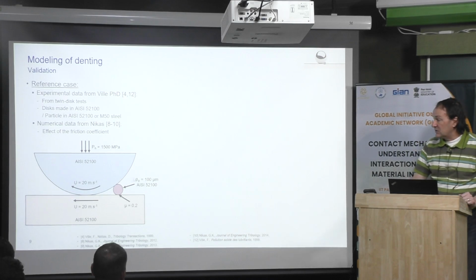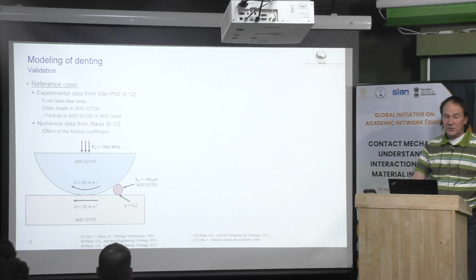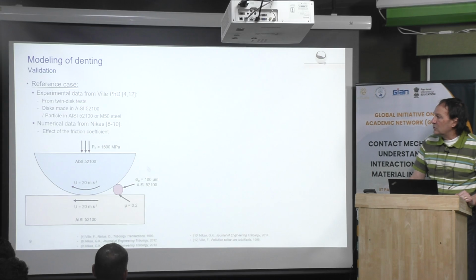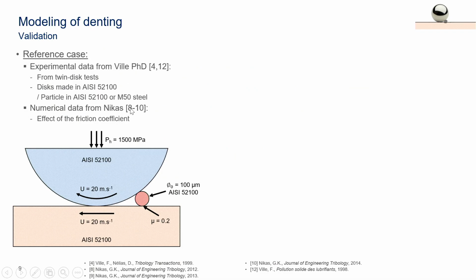Okay. The size is quite large, but this is a reference case, and we were able to do simulation with smaller or bigger particles. And also we compared to some data from experiment and from the literature. In fact, Fabrice Ville did his PhD with me nearly 30 years ago, something like that. Then we have a lot of experimental data. And the maximum pressure is 1.5 gigapascal, which is typical for aerospace application.